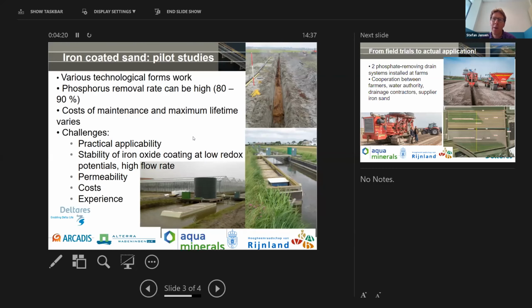And well, the last application is the bottom left picture, where a reactor system was built. In terms of phosphorus removal, this worked well as well. But here we saw that there's more risk of clogging because ditch water was fed into the reactor. And you can see that a pre-filter was needed for this, but even then, clogging issues arise. So clogging can be an issue if you use that technical form.